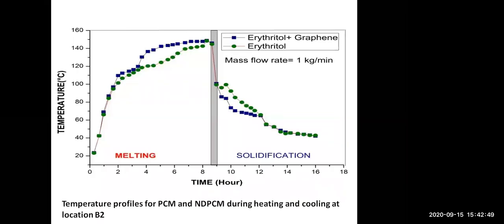One thermal cycle consists of one complete melting and one complete solidification for PCM and NDPCM. The melting time of NDPCM was reduced by 22% as compared with the pure erythritol. It's a significant result. Then the solidification time of NDPCM was decreased by 23% as compared with the pure erythritol. Okay, due to time constraint, we'll go faster.